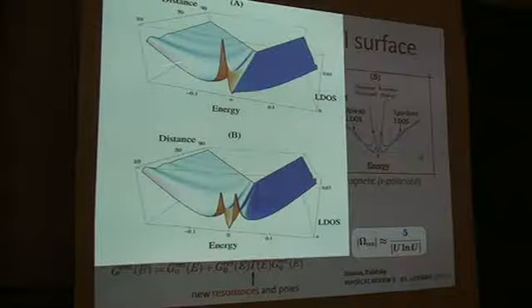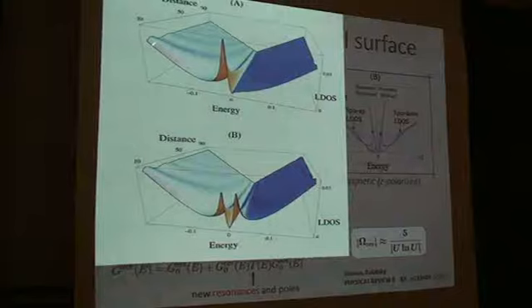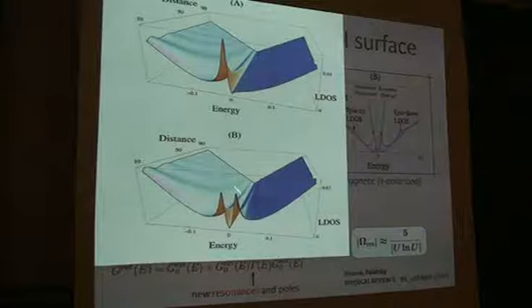So this is the density of states as a function of energy, and then in the plane, those are ripples drawn in Mathematica. This is a continuum calculation where you see how the ripples stay with the relevant wave vector, which is the K Fermi. Because in this case, the topological insulator, we assume that the Dirac cone is at the gamma point at the center.